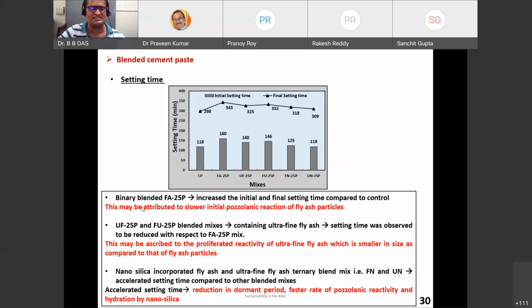So I have mentioned here the binary blended fly ash mix increases the initial and final setting time compared to control. This may be attributed to the slow initial pozzolanic reaction of fly ash particles. As I told you, same thing I told you, and we know it very well. Now when you come to the nano silica, that is accelerated setting time, that is a reduction in the dormant period, faster rate of pozzolanic activity and hydration by nano silica. That is what is happening when I am adding nanoparticles.